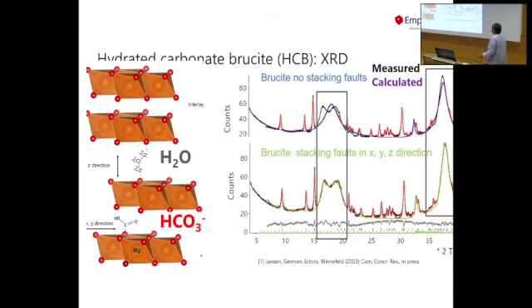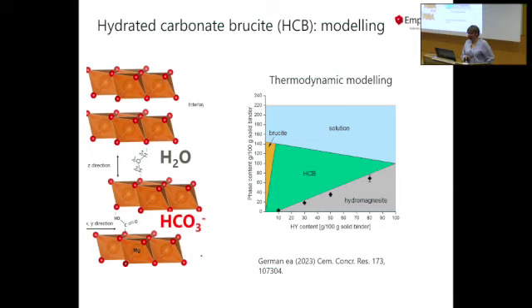So what we think at the moment is that the binding phase in such magnesium carbonate cements is a disordered brucite which has water and CO2 in its structure. And naturally, we also did thermodynamic modeling for this system, and if we do that, we can nicely match the experimental data. So we think we have halfway an idea of how these phases look.